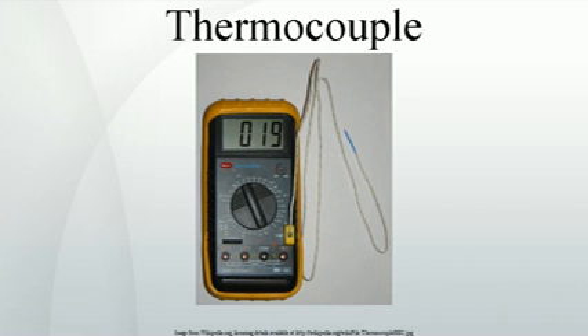Platinum-molybdenum alloy thermocouples. Thermocouples of platinum-molybdenum alloy, Pt/Mo 95%/5% and Pt/Mo 99.9%/0.1%, by weight, are sometimes used in nuclear reactors as they show a low drift from nuclear transmutation as induced by neutron irradiation, compared to the platinum-rhodium alloy types.